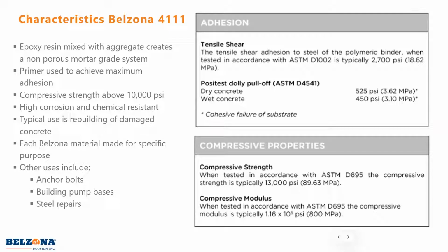So it does set up a lot quicker than normal concrete, where normal concrete would take typically 28 days to be fully compressive. So over here is a little bit of the adhesion we have of it. Your tensile shear is typically around 2,700 PSI, which is superior to anything concrete-wise on the market.